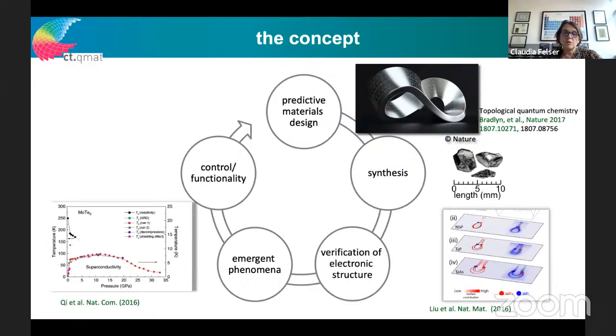On top, we want then to have maybe super interesting properties, the topological material which shows also superconductivity. And there's a lot of recent work on MoTe2, where we found that this is a topological Weyl semi-metal and also superconducting up to 10 Kelvin under pressure.